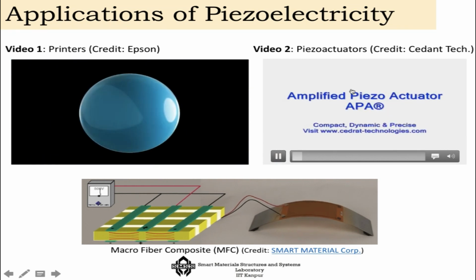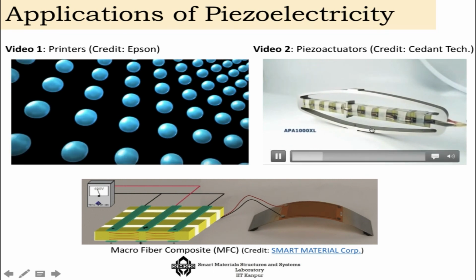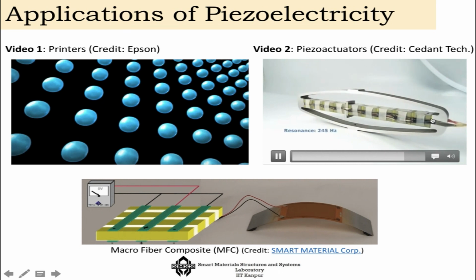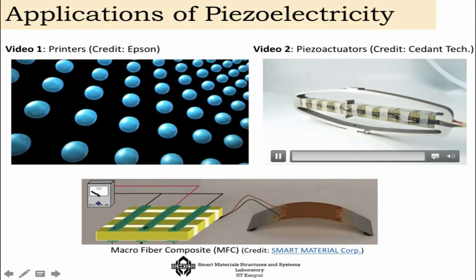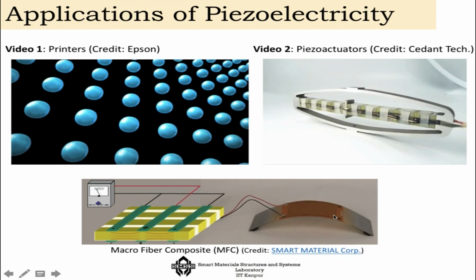Another application is in the amplification of a piezoactuator. If you look at the piezoactuator here, the central part is where the actuation is taking place, and this actuation in the central part is very small, but because we have used a special egg-like structure, a little bit of deformation here can create a large deformation along the semi-minor axis of the ellipse, which is what these amplified piezoactuators do. And look at the very last one. This is where the piezoelectric material is actually in an offset with a composite. Here also, because of this offset, by actuating this, you can get a large deformation out of the system. All these three things you can use in some way or the other in developing actuators.